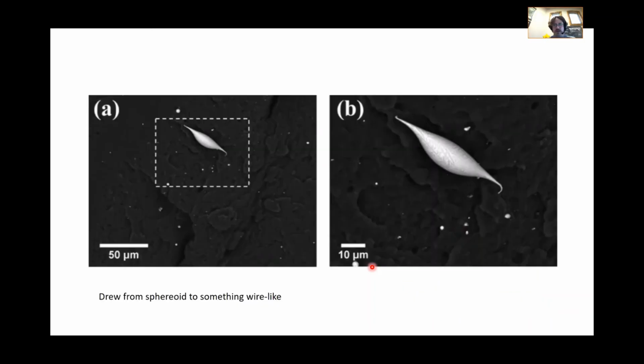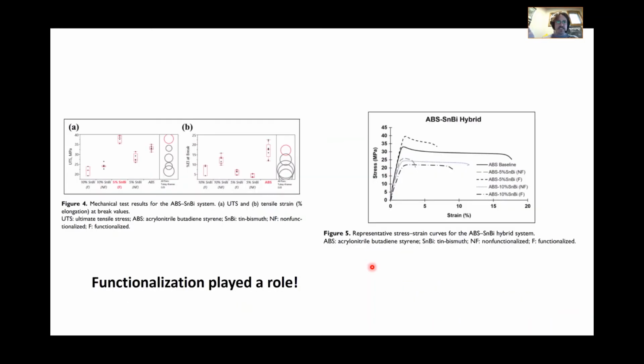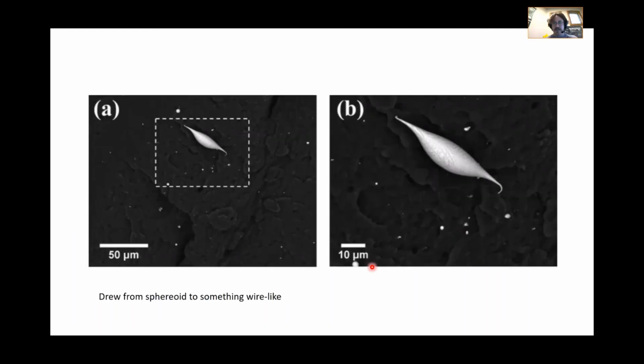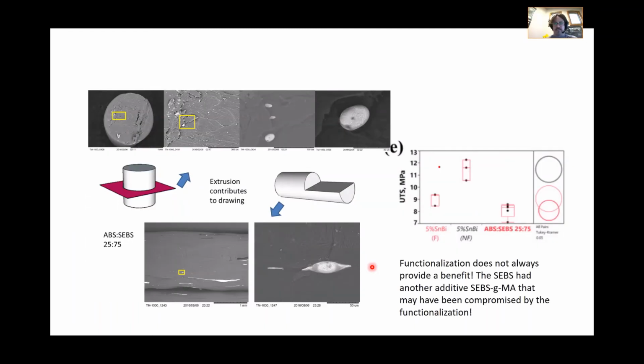So here we see a case where functionalization was beneficial - we saw an increase in UTS. Even though I promised we're not always going to talk about strength, we're still talking about strength. Here I see a situation where the functionalization perhaps was detrimental to what was already there in the matrix. So something else to consider: the chemical compatibility between your filler and matrix, and how you may be altering that as a materials engineer.